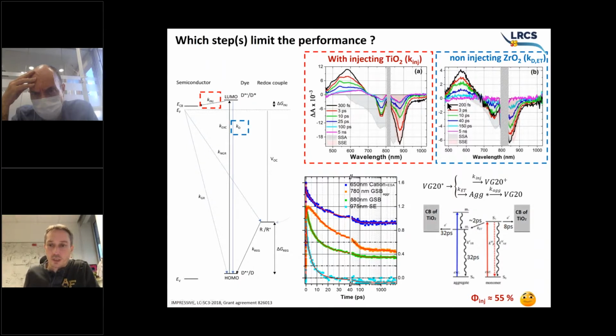They are very similar, and if you look carefully at the decays and analyze all the decays, we spent many months on this, one will find that we have another process which is very harmful for the devices. It's not the injection, but this is energy transfer from the monomer to the aggregates. The aggregates are very problematic for the devices here. So you have an energy transfer from the monomer to the aggregates, which is in 2 picoseconds. And the dye decays within 50 picoseconds.